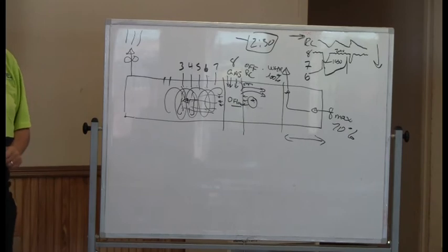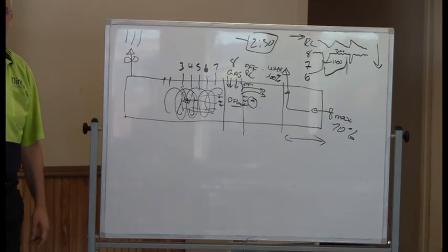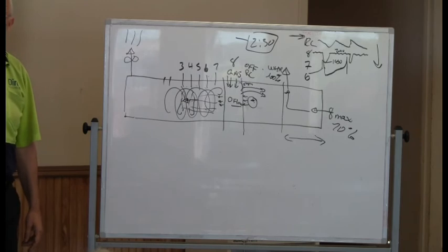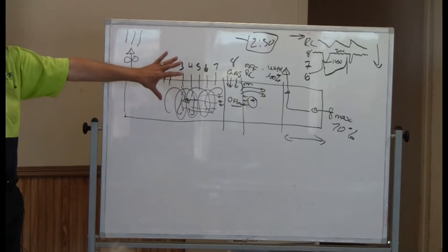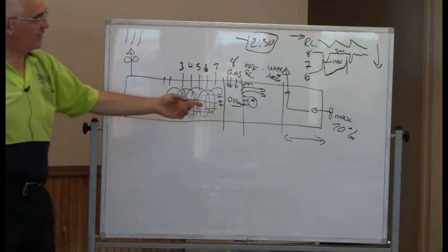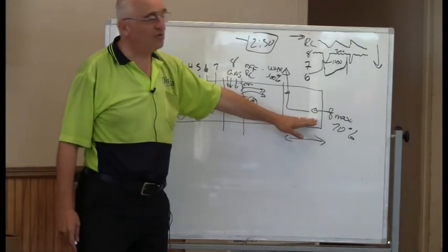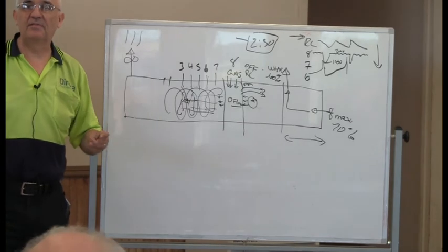And when you have a peephole at the end of the kiln, you actually watch that. If you have the ball of fire at the bottom of the car, it means you have too much air passing through. So just food for thought. Again, it's a principle, but the beauty of that is you don't lose your cooling hand because you actually keep cooling.